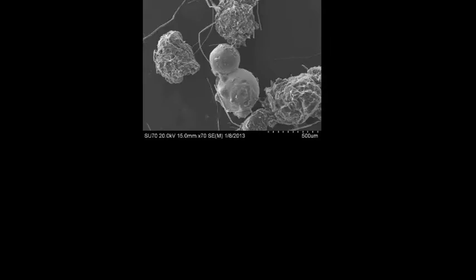To investigate this question about source, I took our samples and I looked at them under what's called a scanning electron microscope. So this is just a really high-powered microscope. It allows us to do elemental analysis as well as looking at them just under a microscope. It lets us look at the texture of them as well as the elemental analysis. So this gives you an idea of some of the images that we can get. This is a scanning electron microscope image in its typical arrangement where it's doing secondary electrons. So scanning electron microscopes use a beam of electrons that they shine onto your sample, and the electrons hit the sample and cause the emission, most often, of electrons from that sample, and then based upon the scattering, or the emission pattern of the electrons coming off, you can get a nice image of the surface of your sample.